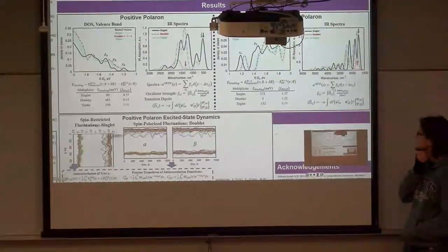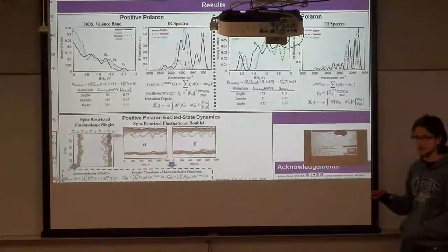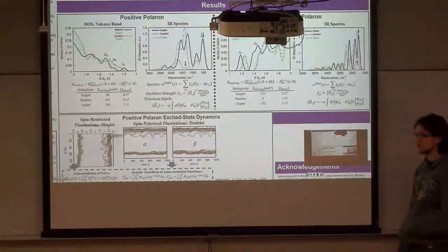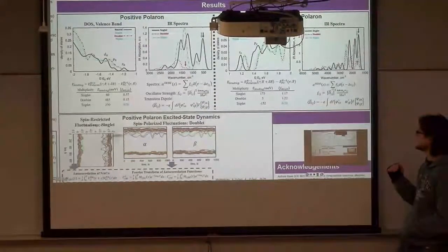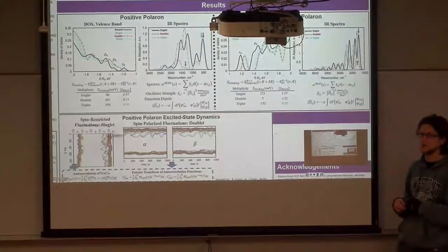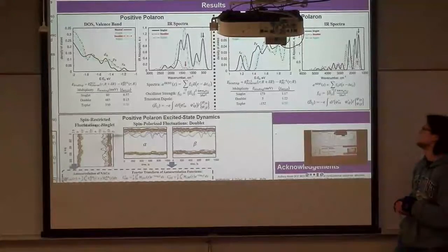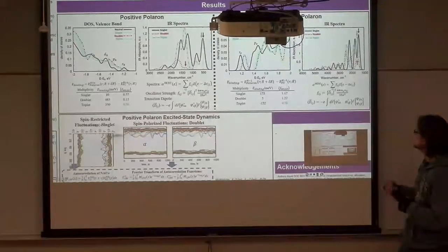Yeah, and comparing that to other results in the literature, they found for a similar model for computation, binding energies consistently around 1 eV. But the main difference is they had an actual cluster. They didn't have ligands, so you could possibly argue that ligands suppress some of the nuclear reorganization at the surface, but it's probably a little bit more. There's probably a miscalculation somewhere too, so I just have to go back and double check those.